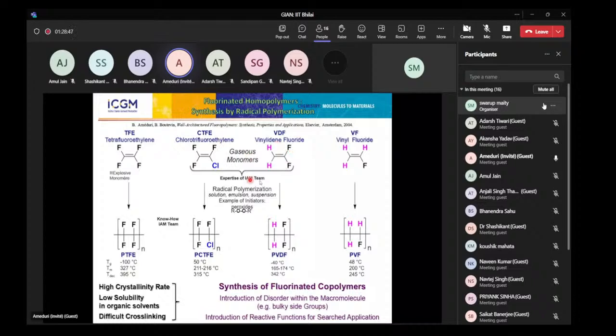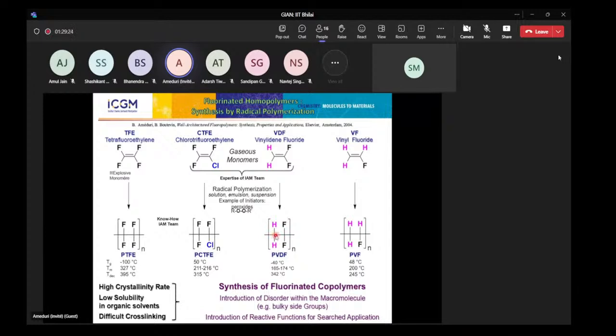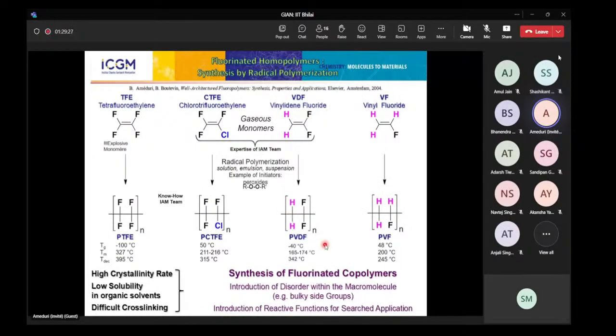Then you have VDF, which is also a gas. So just to mention that all these monomers, TFE, CTFE, VDF, and vinyl fluoride are gases. They have to be carried out in autoclave experiments, vessel. And PVDF is a very nice polymer with a Tg of minus 40 and a melting point lower than that of PCTFE. Its range depends on the defects of chaining, because it's not a symmetrical polymer in which you have some change of organization. Let's say you can have CH2CF2, but also you can have CF2CF2 or CH2CH2, some defects of chaining.